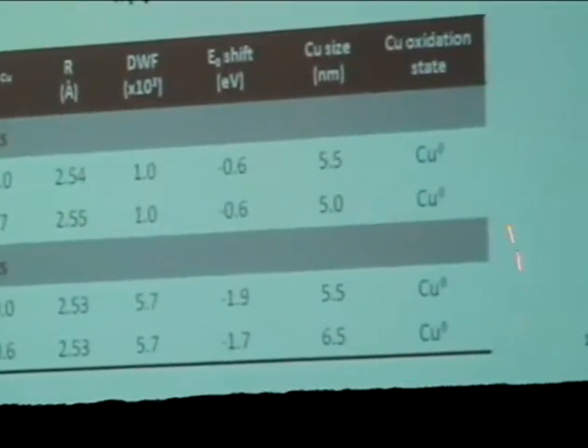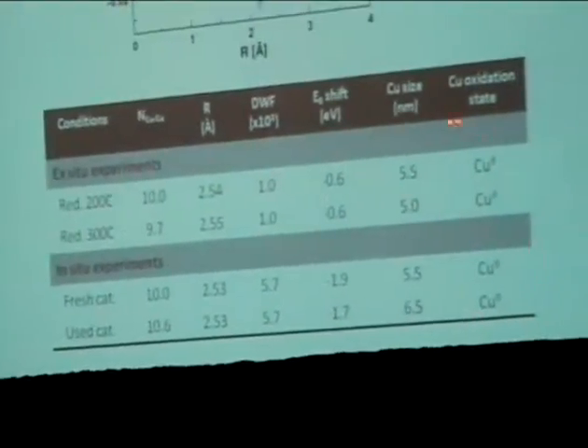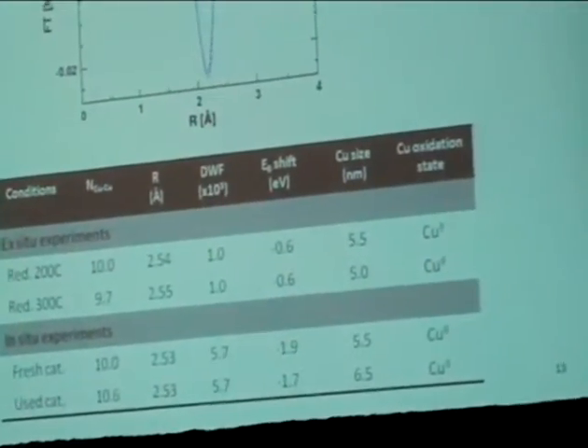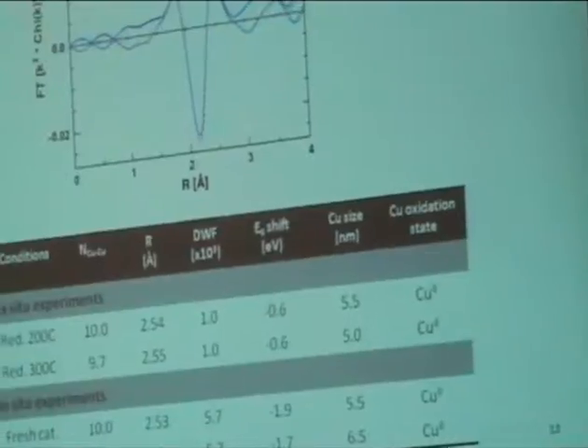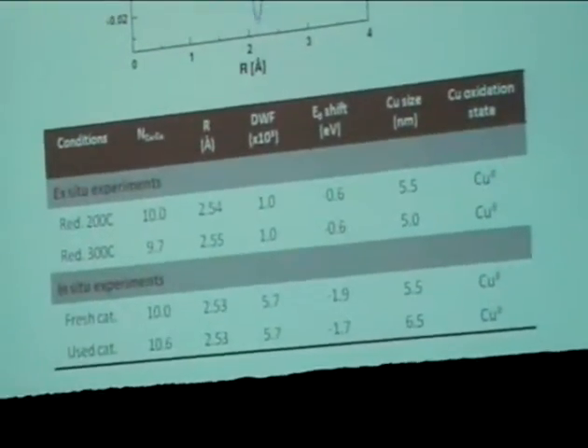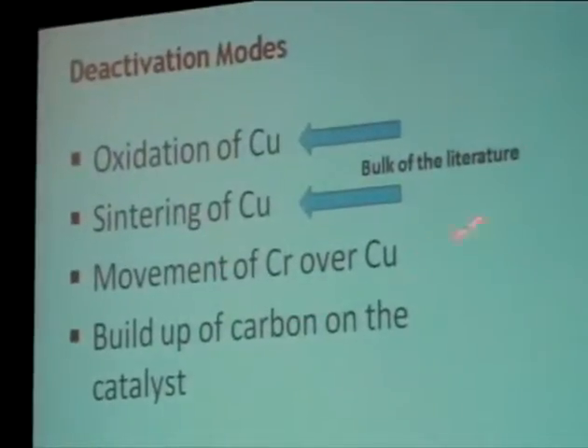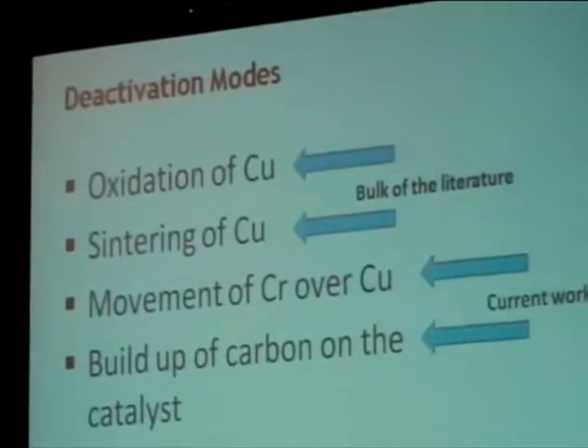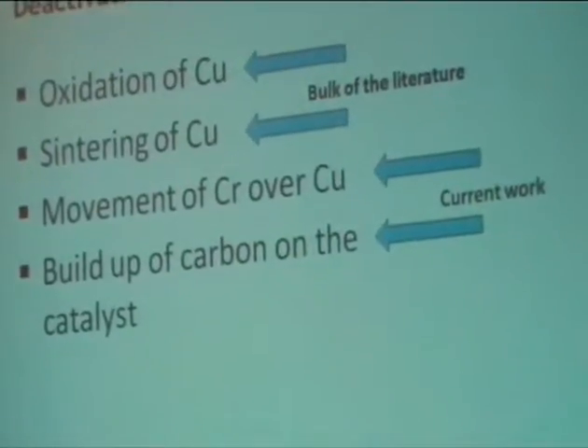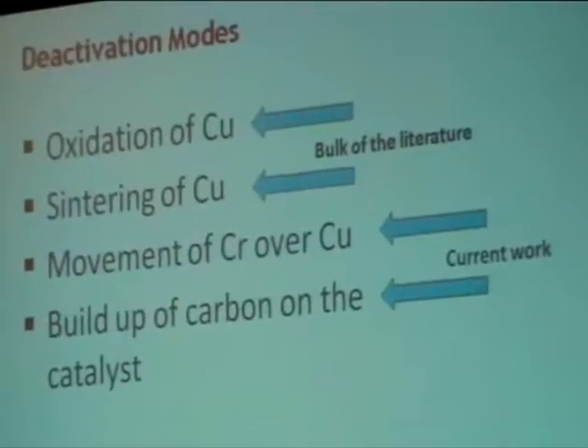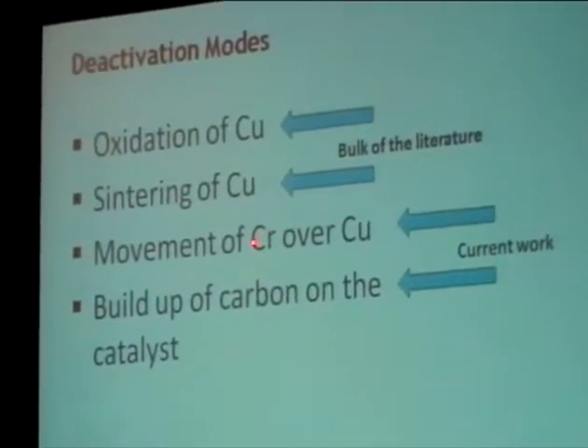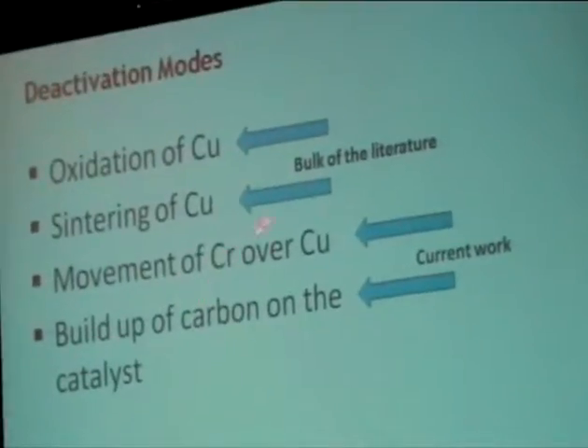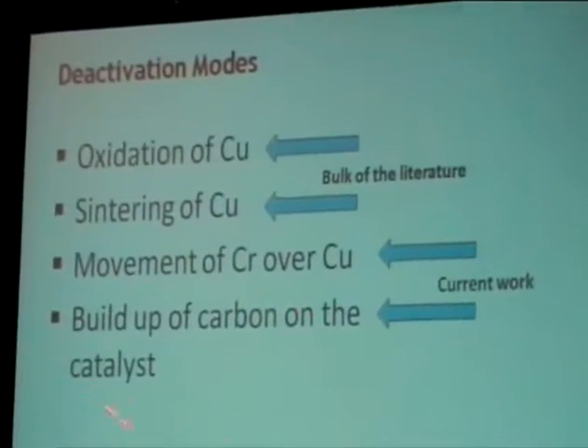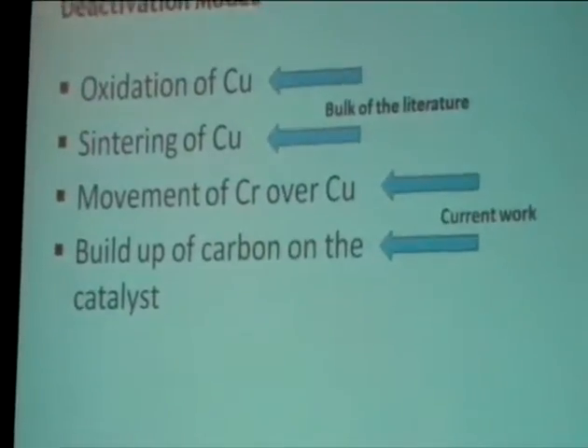In addition, again pointing back to the XANES work, all the copper seems to be in the copper 0 state, and there's no evidence for copper 1 or 2 as the active component, as has been pushed by the open literature. So as I said, the open literature seems to support these. What we believe in our current work is that these are the 2 primary methods of deactivation of this catalyst: the movement of chromium from the chromium oxide sublayer to over the top of copper, and then the buildup of these oxygenated carbon materials on the surface of the catalyst.